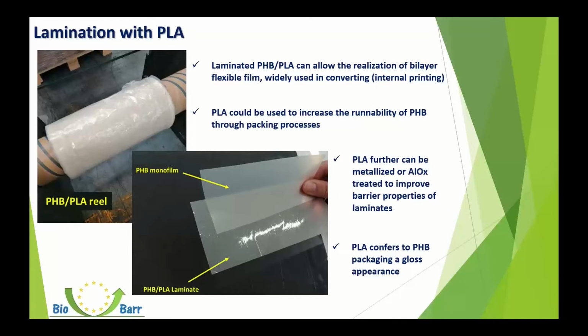The lamination is an important technique in flexible packaging because it is widely used in converting, for example, for internal printing application. The presence of PLA could also increase the runnability of PHB through packing processes, as it reduces the fragile behavior of PHB. PLA can also be metallized or Alox treated to improve further the barrier properties of the laminate. And as you can see in this picture, PLA confers also to PHB a gloss appearance.